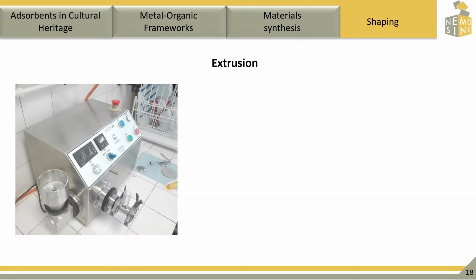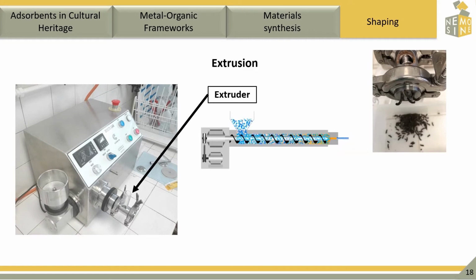So another method that we apply in our group is extrusion. Extrusion is done when a pressure is induced by the rotation of one or two screws that expels a paste formulation through a die with a specific size. The formulation of the paste is important, and the paste to be fed needs to have suitable rheological properties, such as significant plasticity to allow the paste to be extruded through the die with sufficient cohesion that avoids the formation of surface and bulk defects in the extruded products, which can lead to fragilities in the structures, and then they will break and not be suitable for application.